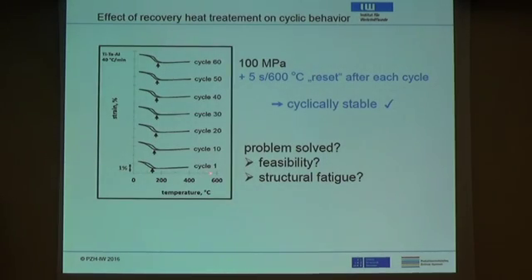So then we apply this to cycling. So you see this first cycle. After this first cycle, you had a very short heat treatment, only 5 seconds, at 600 degrees C, which we call a reset cycle. Then we ran the next cycle, did the next heat treatment, and so on. And now you see that these cycles become stable. You can cycle this on forever without a change in the hysteresis loop. Have we really solved the problem?